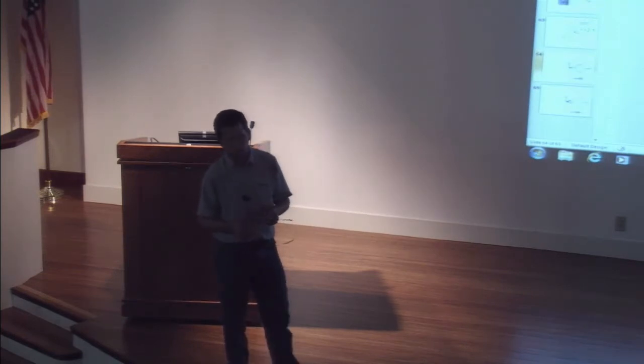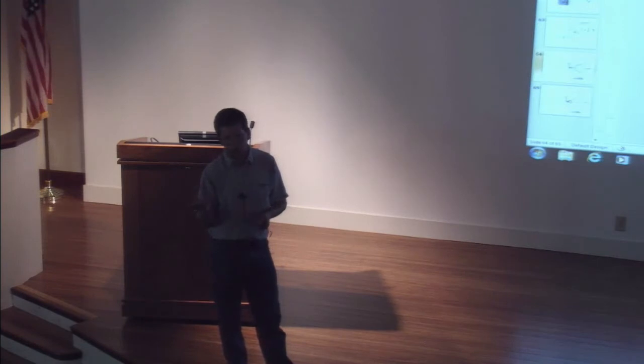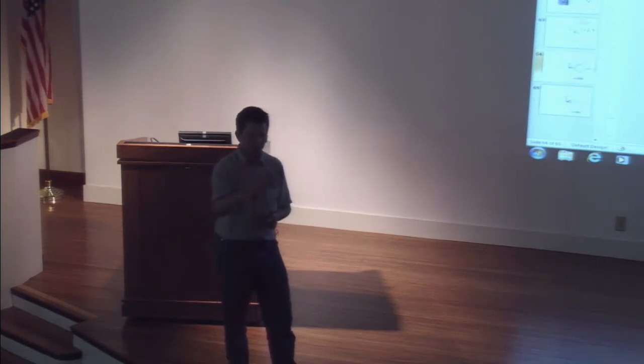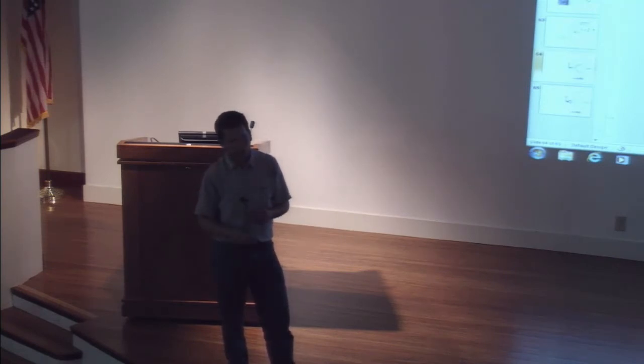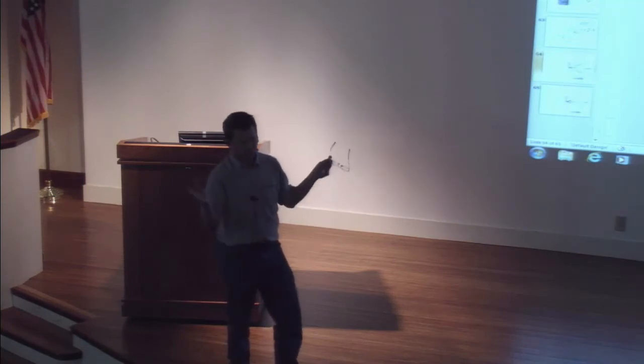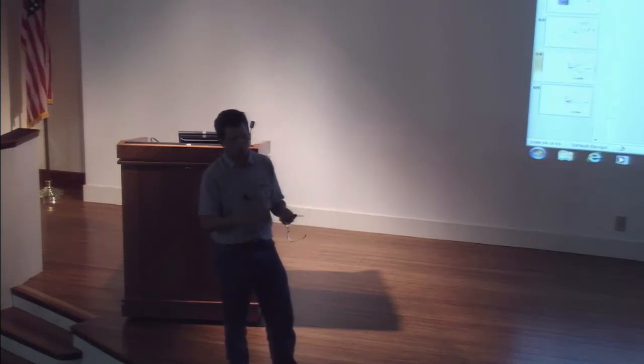The other part that's really helpful: in this case, I was running the program and it was working fine. It was just giving me numbers that I knew were wrong. So the other real important lesson is make sure that you check your law against the data that it was obtained with. And the last one is don't just change the activation energy or the stress exponent without changing the pre-exponential term. Those are the other lessons.